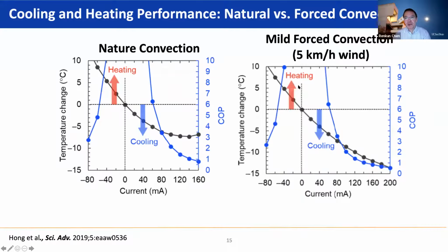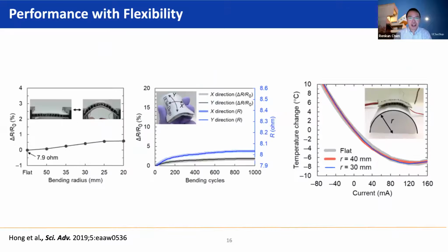And this both heating and cooling as well as COP can be enhanced if you have a very mild wind or forced convection condition. Again, this is also because of better heat transfer from the hot side of the device to the air. And we can show that the device actually is flexible. We can bend this for about 1,000 cycles with not much degradation, and the performance is the same when it's either flat or curved.